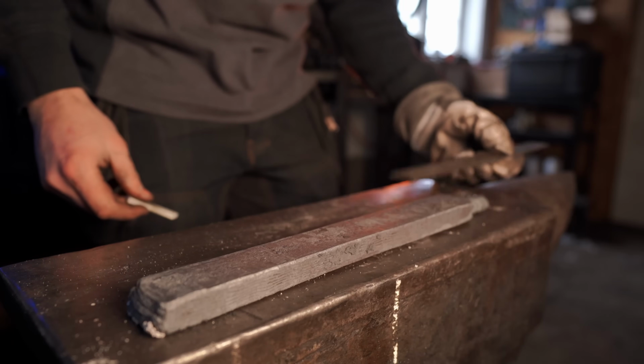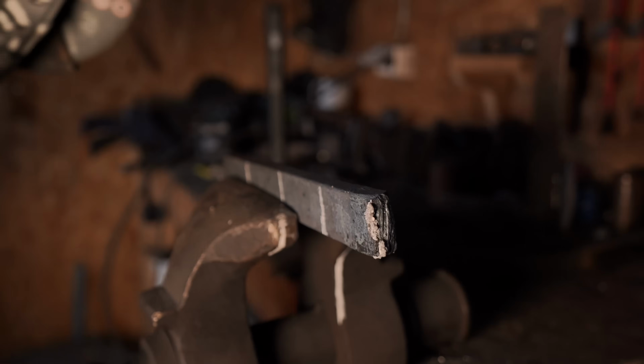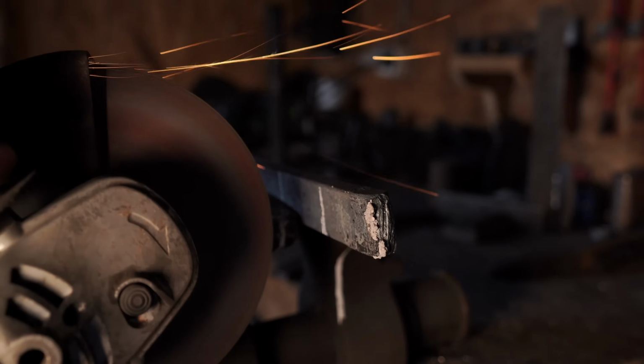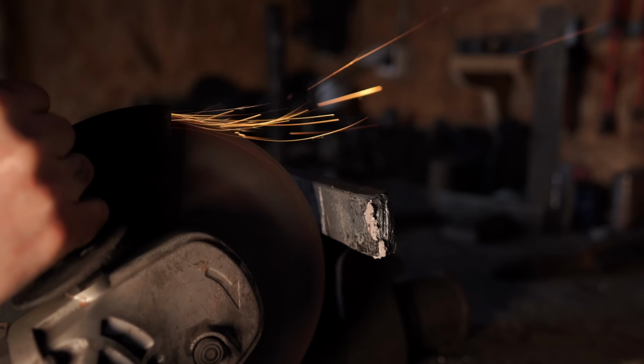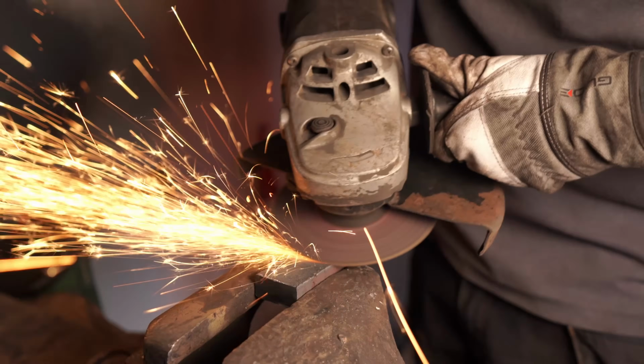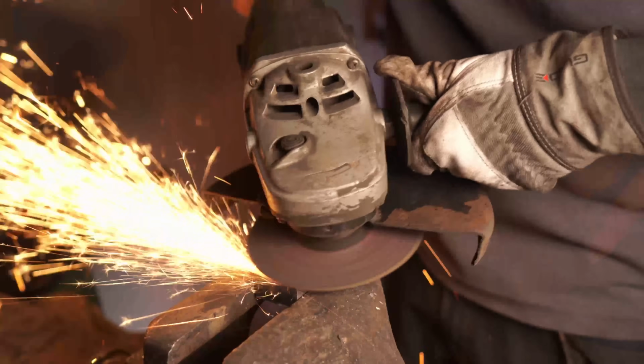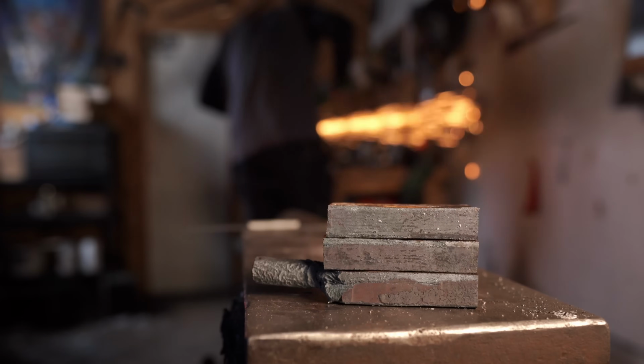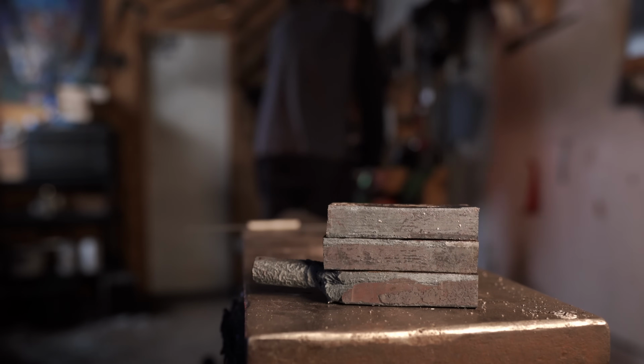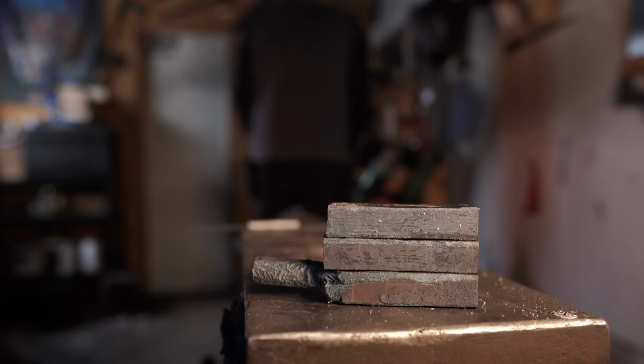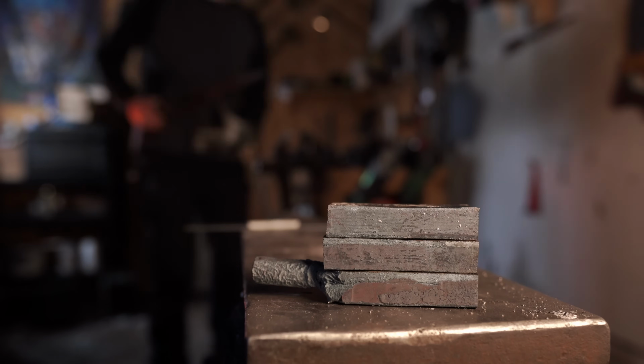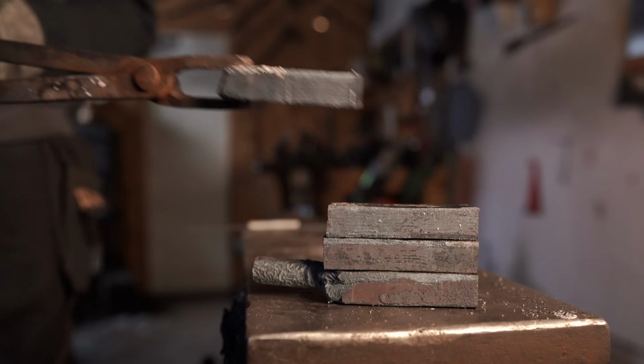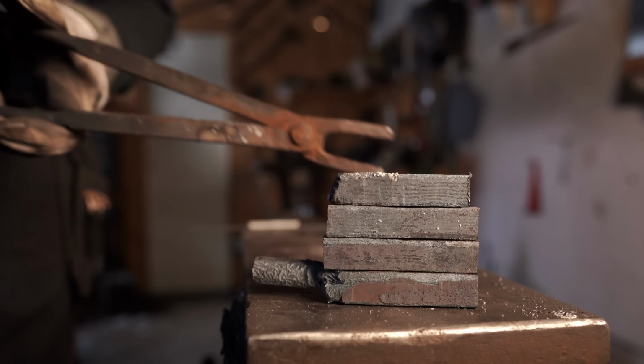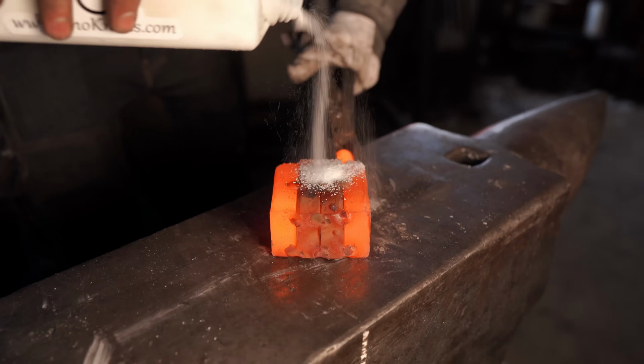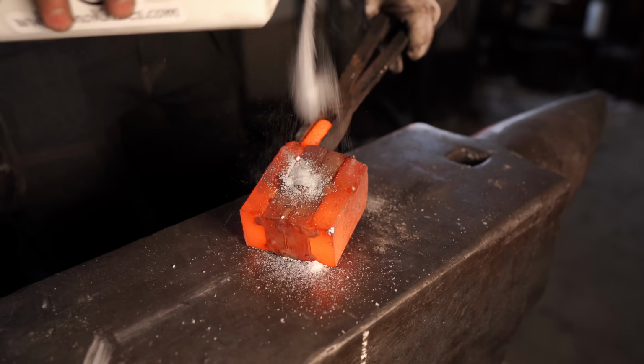Once the billet is forge welded and drawn out, I'm going to do a restack. That means that in this case I cut the billet into 4 pieces, stack them back together and repeat the entire welding process. What this does is that it increases the layer count of the billet. So I started with 24 layers and now with the new stack the layer count should be closer to 90 or somewhere in that ballpark. Now, I'm well aware that 24 times 4 is 96, but some layers may have been lost due to grinding and scale forming, so it's better to go with a rough count.